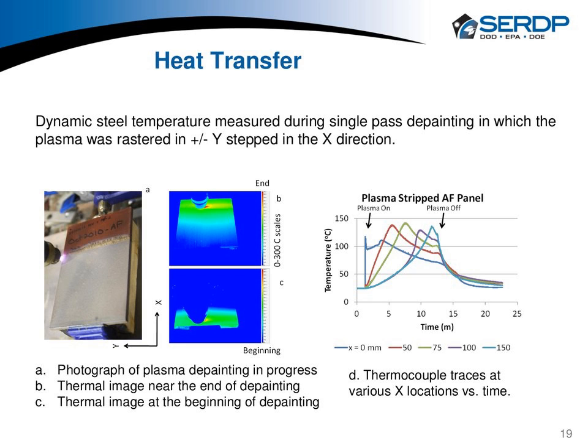So in this particular example, we placed a series of thermocouples to demonstrate this at various positions, which are shown here at 0 millimeters, 50, 75, 100, and then all the way to the end. And then we rastered the plasma across this surface to effect paint removal. And here's a thermal image of that at the beginning and the end. Here's a real photograph of the plasma in action. And then the thermocouple traces at each one of these positions.